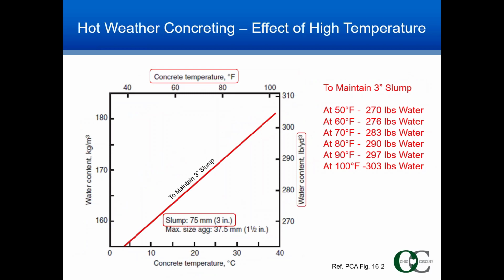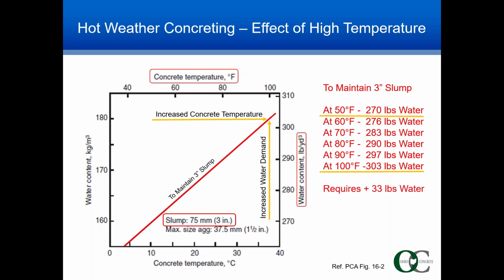Consider the batch water required to hold a 3-inch slump with increasing concrete temperatures. As concrete temperature increases, there is a loss in slump that often is compensated for by adding water to the concrete at the job site. At higher temperatures, a greater amount of water is required to hold the slump constant. As shown in this graph, if the temperature of freshly mixed concrete is increased from 50 degrees to 100 degrees, about 33 pounds of additional water is needed to maintain that same 3-inch slump.